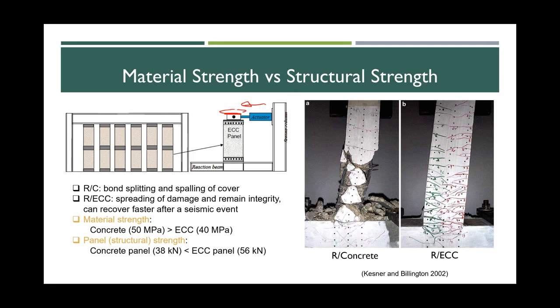And compared to this material strength, we built this concrete deliberately higher, like 25% higher than the normal ECC. But as a result, the panel structure strength actually is higher. So with lower strength materials, we actually build higher strength ECC panels. So that's how material strength cannot directly represent the structure strength if they have other properties.